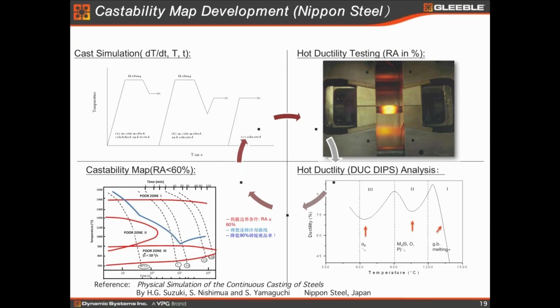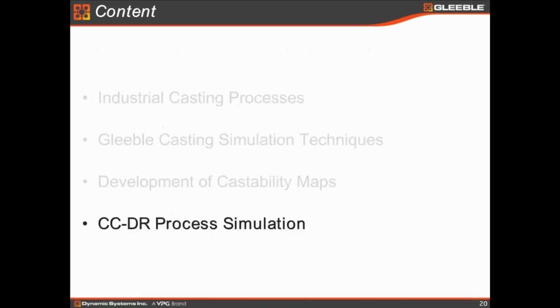What I'm telling you is their surface treatment rate dropped from 45% down to less than 5%, which makes CCDR a reality. So now, for all the new steels they are developing, you have to develop a castability map before you can tell your caster operator how to cast, because the speed is really a strain rate in terms of the Gleeble simulation, cooling rate, and solidification rate. It's all so important, including when to unbend. So again, this technology is very important. I hope this will be useful for all your new steel development and casting.